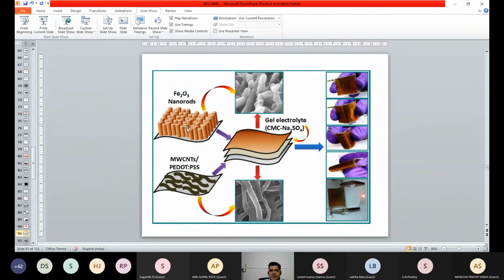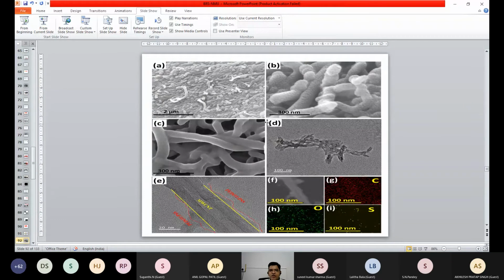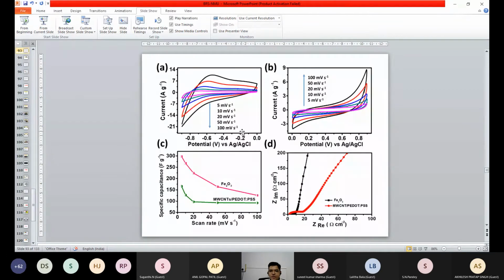Whatever iron oxide there is, we observed it in a nanorod-like structure, which is coated on the stainless steel. Because stainless steel acts as a nucleation site for the iron, we have grown iron oxide in the nanorod-like structure form. This is one electrode. The second electrode is carbon nanotube coated with the polymer, right? And then we have used the electrolyte, that is CMC with Na2SO4, right? And this is the asymmetric type of device. So here you can see this is Fe2O3, this is carbon nanotube, and this is carbon nanotube coated with the polymer. This is with the liquid study.